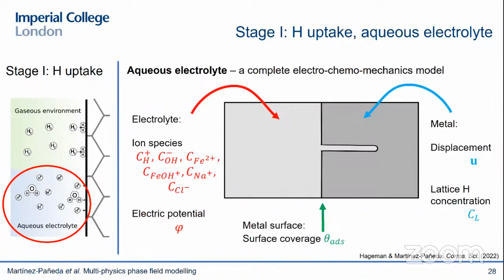And at the end, all of these are degrees of freedom in your finite element model. So you solve for as many ionic species as needed in the electrolyte, for the surface coverage in the interface. And then in the metal domain, you solve for the displacement and the lattice hydrogen concentration, among other things. So you end up easily with, I don't know, 10, 15 degrees of freedom per node. And of course, solving this 10 years ago was unthinkable, but I think computers have gone quite a long way since then. And we have also developed in my group new computational procedures that can significantly accelerate these calculations.